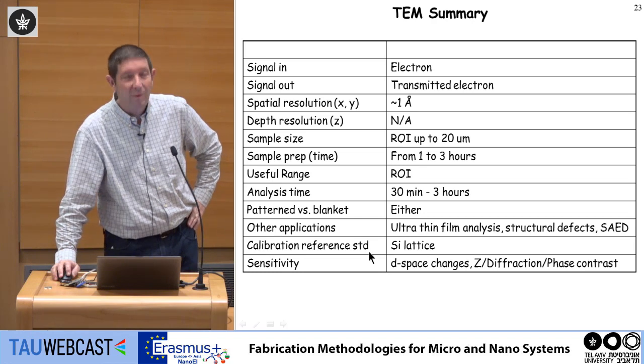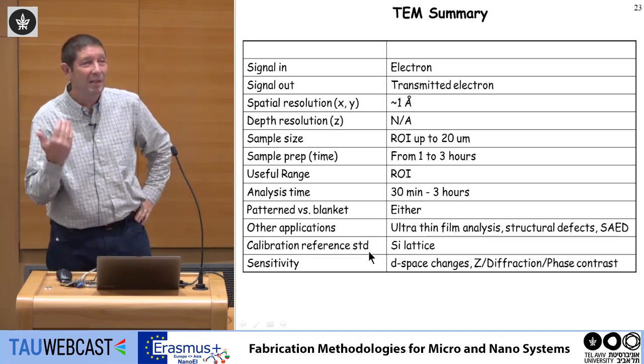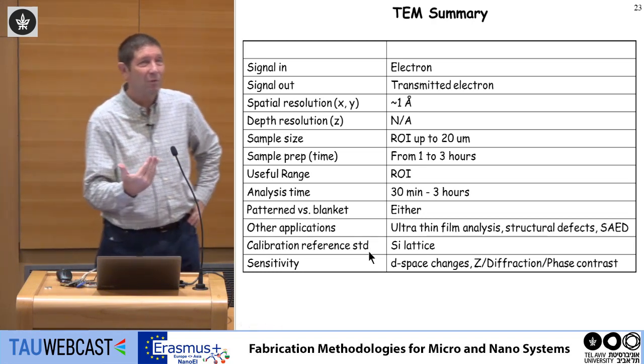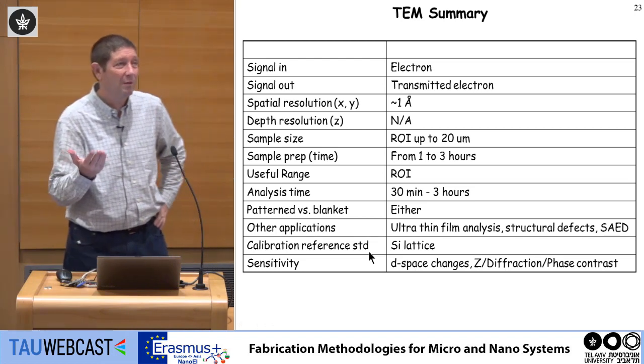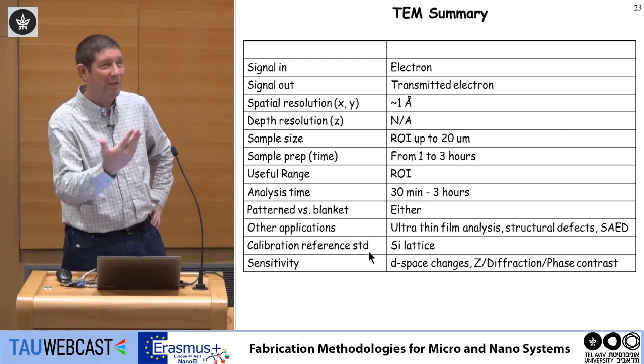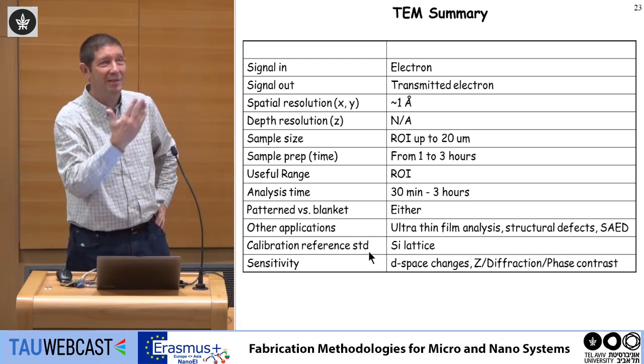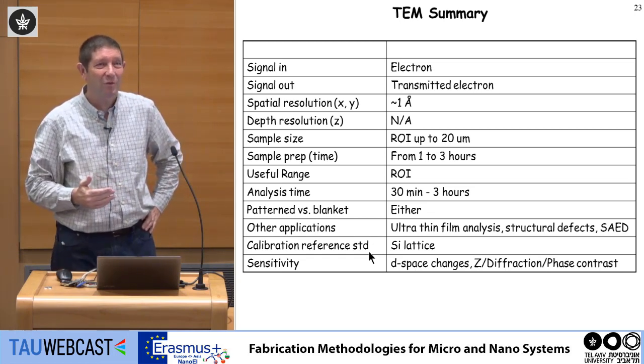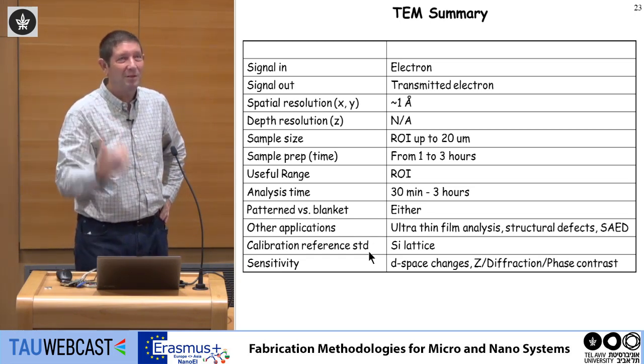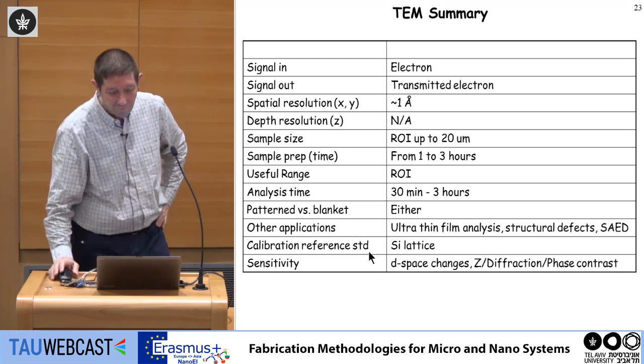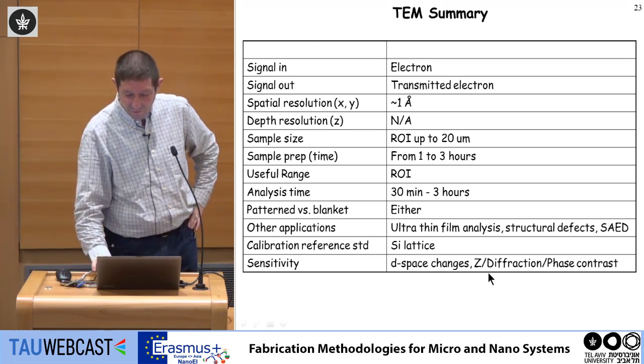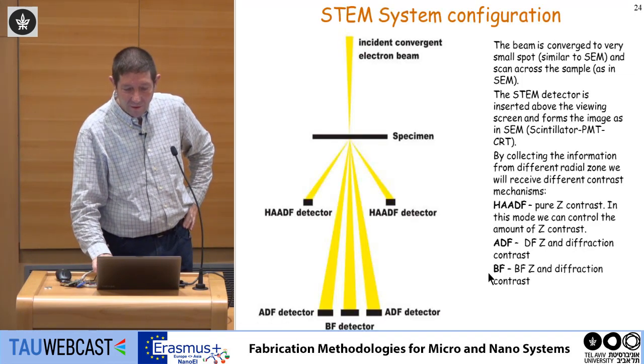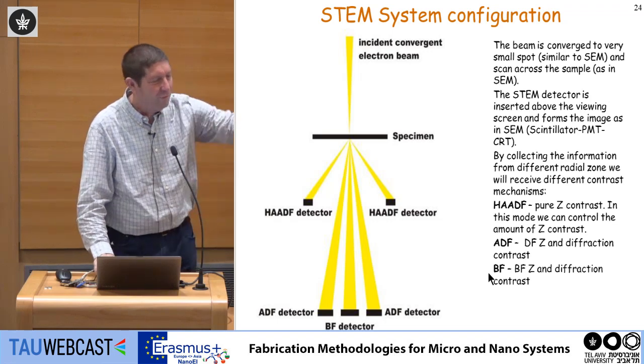Calibration reference, by the way, you don't need, because you can use the silicon itself as a reference, because this is an atomic level, atomic resolution system. So just look at the silicon, and we know the distance between the atoms of silicon. So if you want to calibrate it, you use the substrate as calibration. It's very sensitive. There's another, I want to steal a few more minutes from the break.